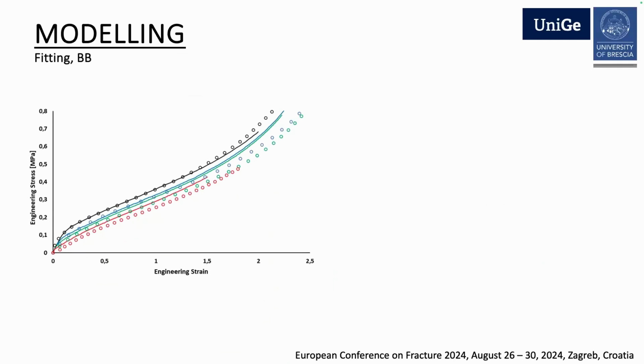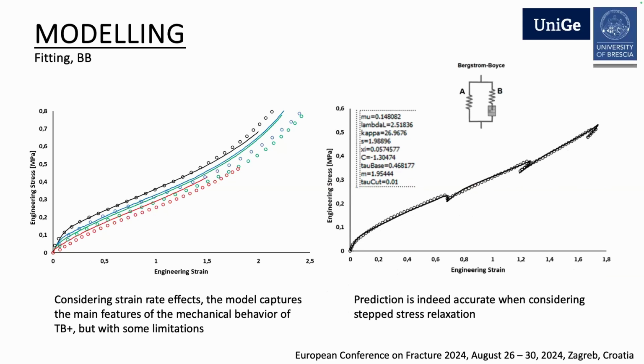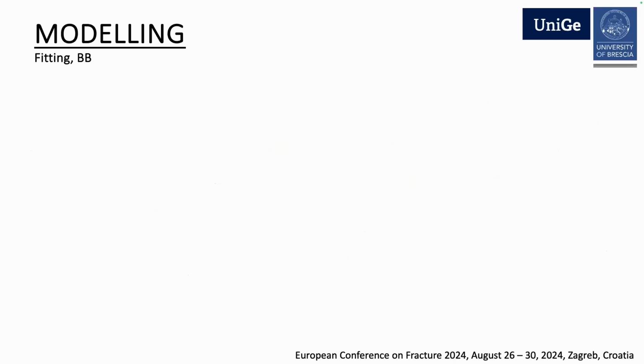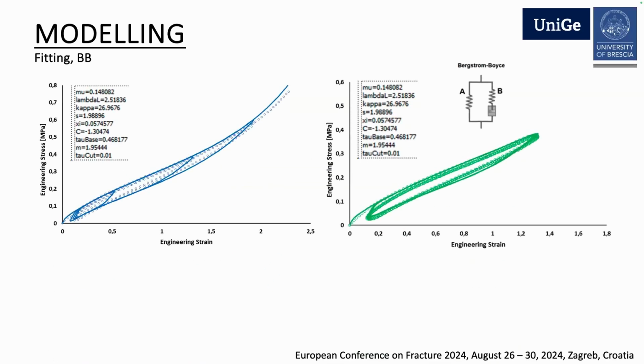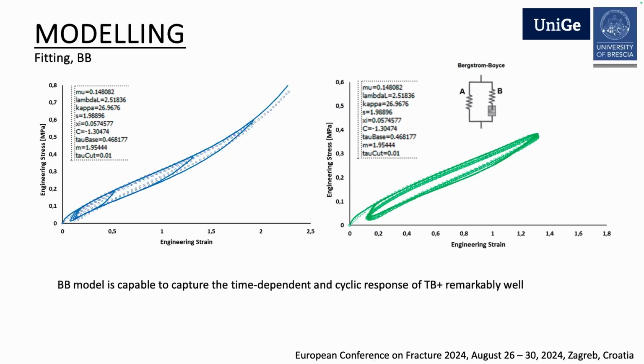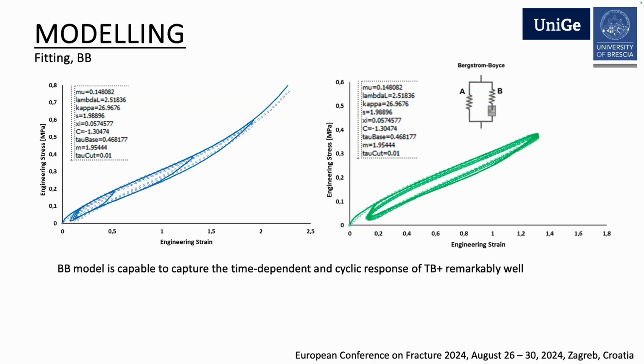In terms of fitting capabilities, you can see the fitting of the Bergstrom-Boyce model against the strain rate. You can see that qualitatively the results are, let's say, good, but for this specific type of test, we found that you have to choose whether you want to be more accurate for the highest strain rate, or you want to be more accurate for this test, which was run at this lowest strain rate. On the other hand, if you consider with the same set of material parameters the other types of responses, for example, here you can see the prediction for the step stress relaxation. And here are the predictions for the cyclic response. I would say that the model actually performed remarkably well, considering the complexity and the differences between the various load cases that we tried to reproduce.